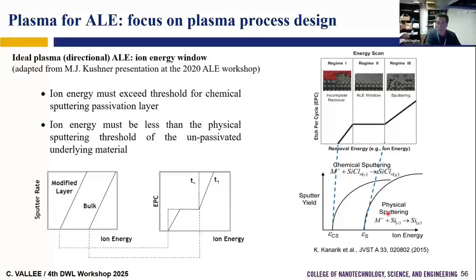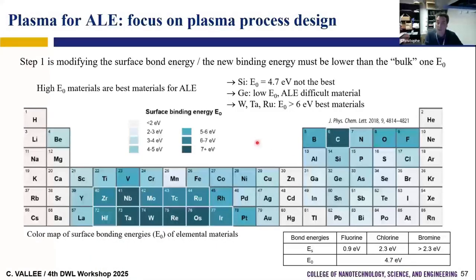So what is illustrated here? When we do the modification of the first surface layer, we have a given sputtering threshold, and the silicon atom in the bulk doesn't have the same sputtering threshold. So if we come with the ion energy in between, we should remove only this atom at the surface, and we should not remove the atom in the bulk. So we have an optimum ion energy to select. If the energy is too low, we do not remove this atom, so we don't etch. If the energy is too high, we sputter also the bulk, so we don't have a self-limiting process where we remove only one monolayer. So what is important is how you can modify the surface energy compared to the bulk.